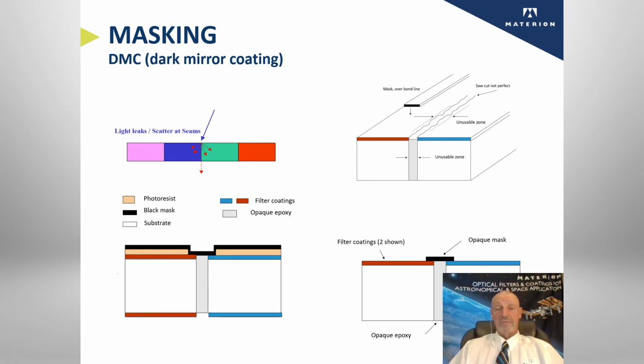So now that you have the assembly made, you want to put on the dark mirror mask to further reduce stray light and reflection in that transition zone between each individual band. We use a photolithography process and a PVD coating specifically designed to meet reduced reflection in the wavelength range that we're talking about. And in the bottom right here, you can see we end up with a very defined opaque mask covering all the transitions between each band.